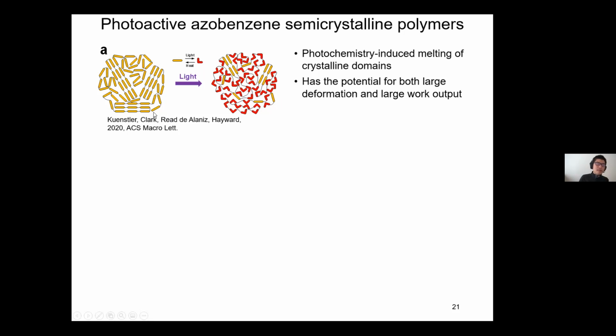There are some crystalline domains and some amorphous domains. Now, of course, this semicrystalline polymer, if you heat it up, it will melt to a polymer melt. But more interestingly, if you shine a light on this, these trans molecules can still go to cis, and now these crystalline domains, they demonstrated in experiment, can melt. So you have a light, and this light can induce a melt of the material. So you see that because this is a semicrystalline material, which sits between an amorphous and a completely crystalline structure, it has the potential for both large deformation and large work output. Experimentally, it hasn't been demonstrated yet, but that's the hope, right?